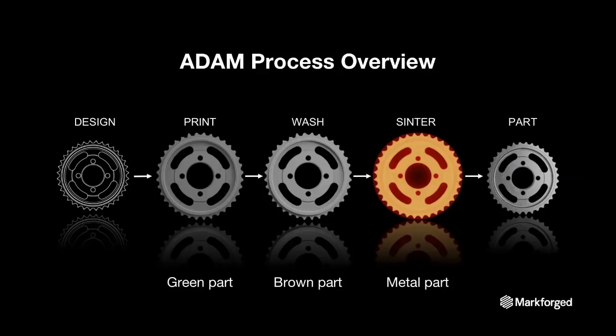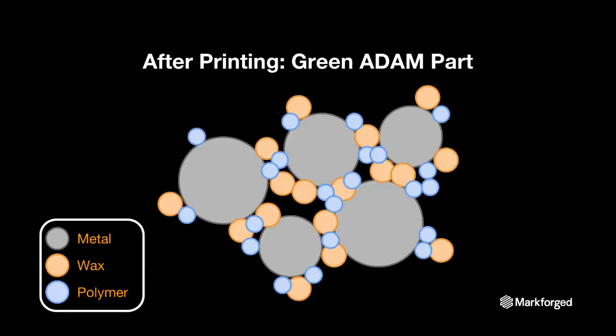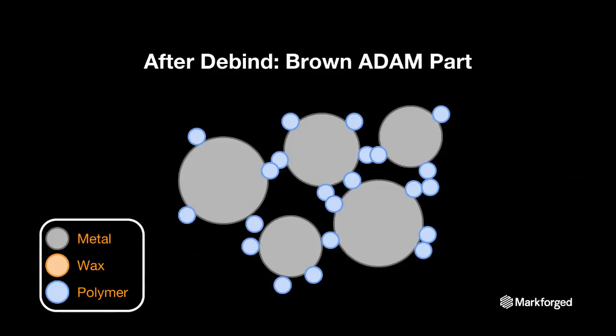And just to give you a little more insight into what this looks like from a microscopic view. If we're looking at the various constituent parts of an ADAM part, you're going to have a metal powder, a wax, and a polymer, as we talked about. At a microscopic view, a small section of your part might look something like this after printing. A green part is composed of all three of those materials. When you put the part through our debinding process, our wash, it's going to remove that wax. So you effectively have a part that looks something like this. The part has not changed in dimensions during this washing process, but it's removed some of that wax. So you now have a part that's semi-porous, and that's actually important for later on in the process. You've basically removed all of the wax binder, and so the part is composed at this point of the metal powder, held together by that polymer or plastic binder.